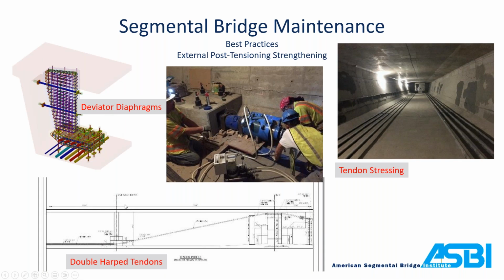Internal post tensioning, this is where you do have those issues with inadequate tendon reinforcement in your bridge, the structural capacity. US 31 over Muskegon was just that. We had a lot of shear cracking and that anchorage cracking that we talked about because we didn't have enough reinforcement around the anchorages or in the shear zones. So we did an external tensioning project with deviator diaphragms and then double harp tendons. And you can see how the tendons harped up through the pier diaphragms and then back down, and then we stress these things and basically squeeze the bridge back together, close the cracks up.